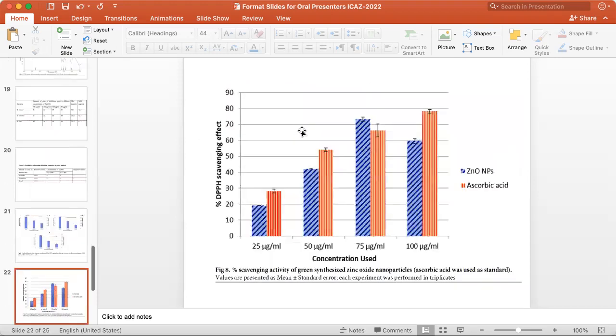At the end, we have also tested the antioxidant potential of ascorbic acid, which was used as a standard in the DPPH assay, as well as nanoparticles, and different concentrations were tested. You can see here, in case of ascorbic acid, there was a dose-dependent response in antioxidant activity. By increasing the concentration, antioxidant activity increased. Whereas in case of zinc oxide nanoparticles, initially there was an increase in the antioxidant activity, but at the highest concentration tested, the antioxidant activity was reduced, probably because of lower solubility of nanoparticles. This might happen.